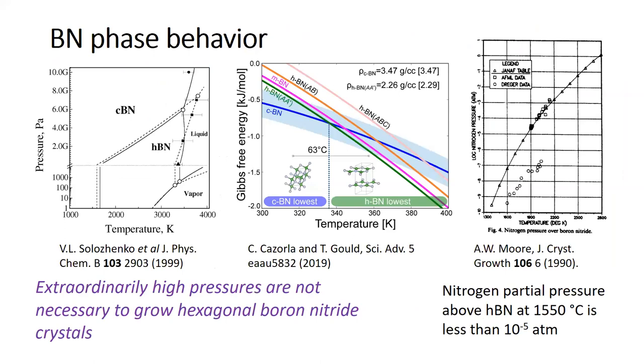But I contend, and actually what those researchers also showed, is that you don't need such high pressures to grow high quality crystals. If we look at the phase diagram of boron nitride, first thing to note is where the liquid appears. It's above 3000 Kelvin. So you're never going to melt boron nitride, or I shouldn't say never, somebody's going to be clever about that, but it would be very difficult to grow from the melt. So that's why we use a solution. It's like dissolving sugar into water. You're not melting the sugar, you're dissolving it into water.